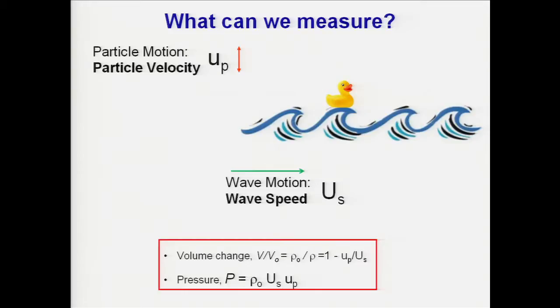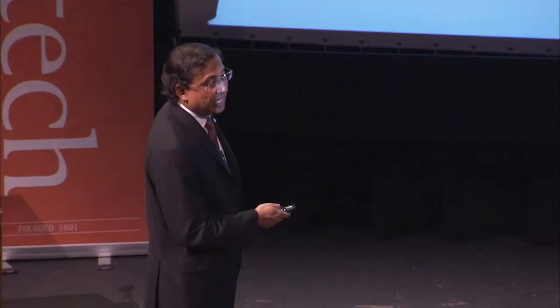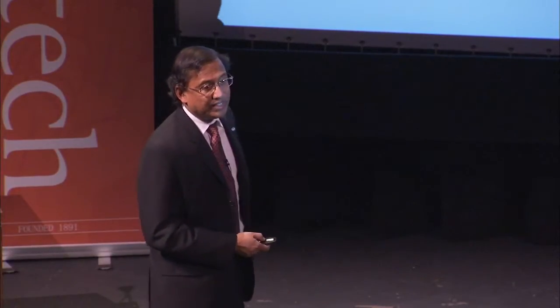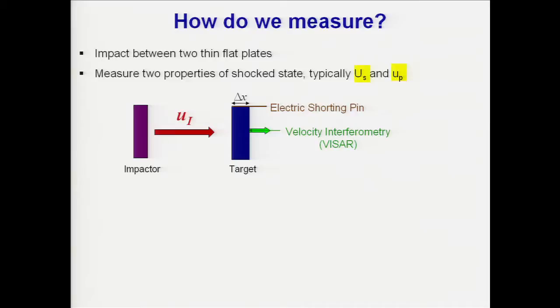So that gives you, as I mentioned earlier, the volume change, and then we can also measure the pressure because we are measuring the particle velocity and the wave speed. And how do we measure this? We use very simple ideas. Here we have an impactor which is impacting, as I mentioned, between 1 and 2 kilometers per second on a target. The target is of interest because we want to understand its material properties. We use an electric shorting pin, so when the impactor impacts the target, an electrical signal is generated. At the same time, we are measuring the rear surface motion because there is a wave propagating through the target. When the wave arrives here, we can measure using velocity interferometry when the shock wave arrived.